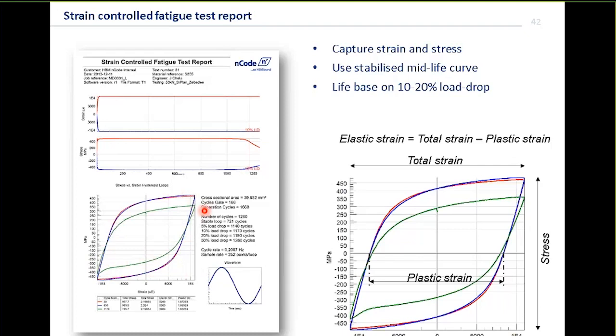So typically, what we do is we look for a particular load drop. Different people have different ones, either 10% load drop or 20% load drop, and that's when we define that the crack's sufficiently long that we've reached the end of the initiation life. The other thing that we take away from these tests is usually about the stable point in the middle of the test, we capture the loops. So in this case, it's probably going to be about the blue loop.